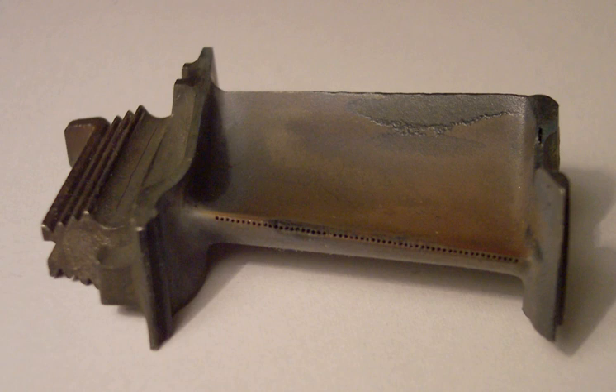Topic: different types of coating. Historically, three generations of coatings have been developed: diffusion coatings, overlay coatings, and thermal barrier coatings. Diffusion coatings, mainly constituted of aluminide or platinum aluminide, are still the most common form of surface protection. To further enhance resistance to corrosion and oxidation, MCrAlX-based overlay coatings (M equals Ni or Co, X equals Y, Hf, Si) are deposited on the surface of superalloys.